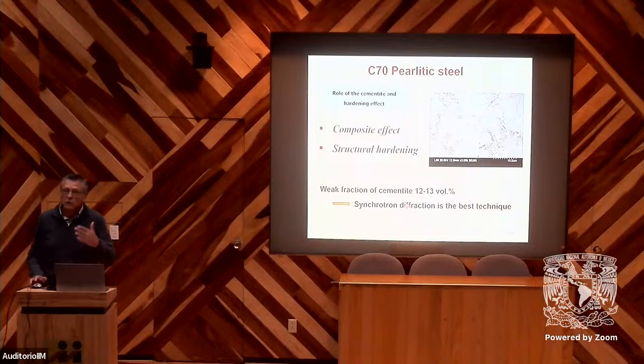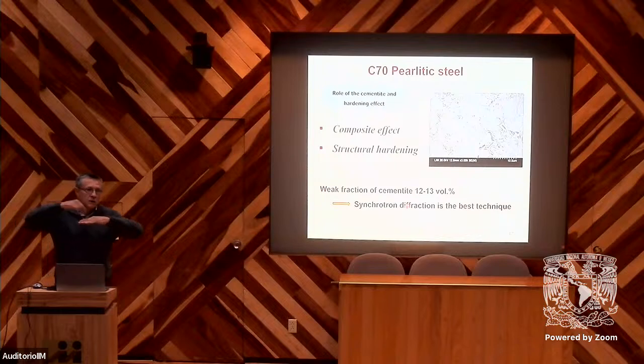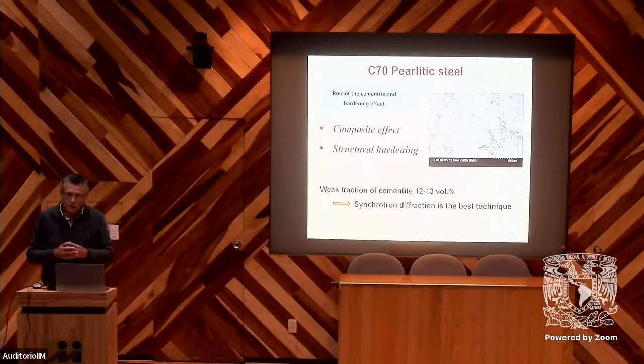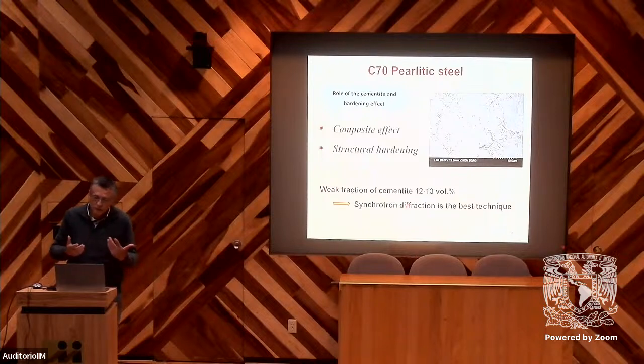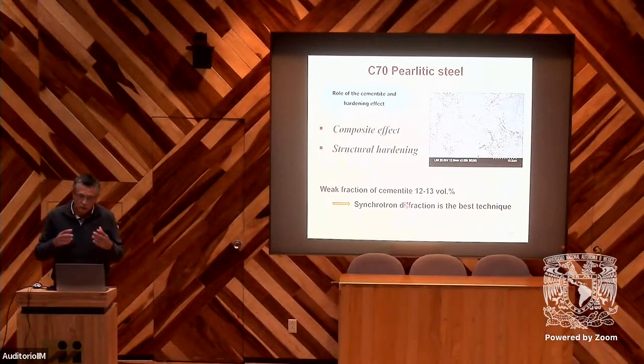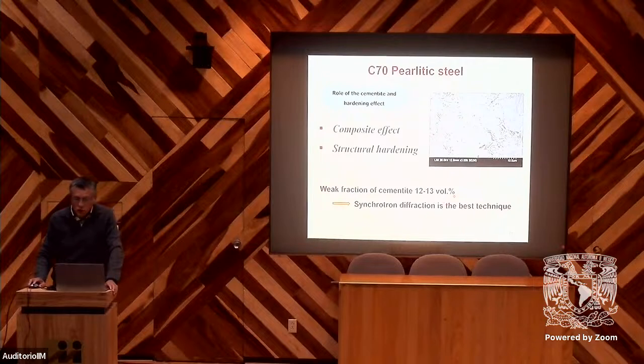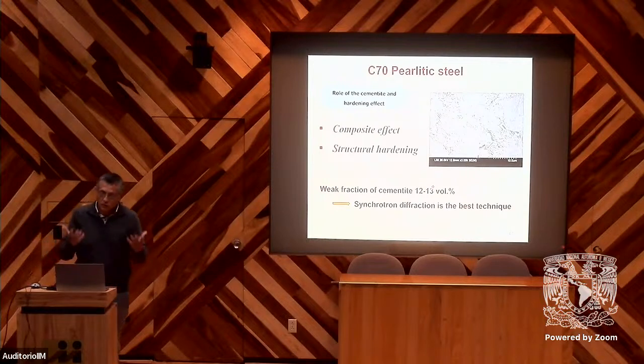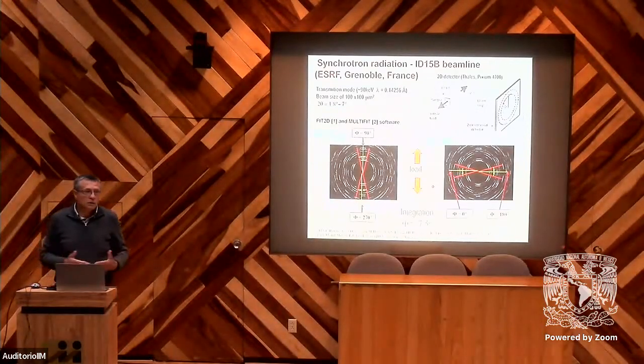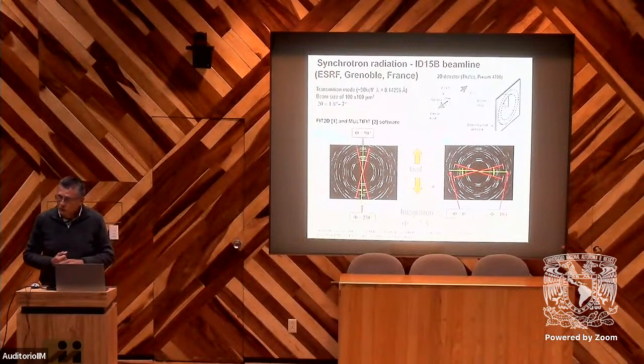It's very difficult, because in some cases you can make some microhardness measurements, but in cementite it's very difficult. So there is no data about the behavior of cementite, and here we need to understand the effect of the hardening by the cementite. We have, of course, the composite effect, but also we have a structural hardening due to the presence of these carbides. The problem here is that the fraction of cementite is very low. So that means we need to use synchrotron radiation, because the intensity will be high, so we can have some information about the cementite.